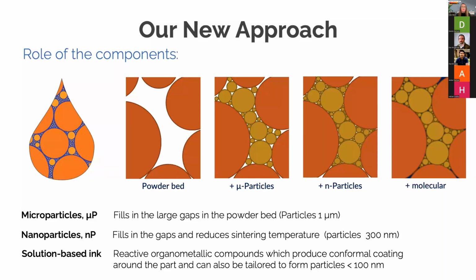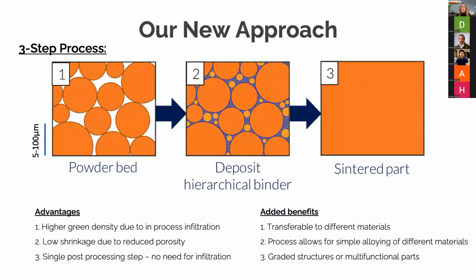We've then got the nanoparticles. They also fill in some of that porosity, but they can act as sintering agents and also microstructure agents and modify the microstructure of the resulting part that you've printed. We've found that we can control the size of the grains in our copper printed parts just by modifying the size and the quantities of the particles in the binder. So those reactive solutions of the components can be tailored for conformal coatings of metal and ceramic. So you're infiltrating and binding with real build material and not sacrificial binders, which is what you normally see in conventional binder jet systems.